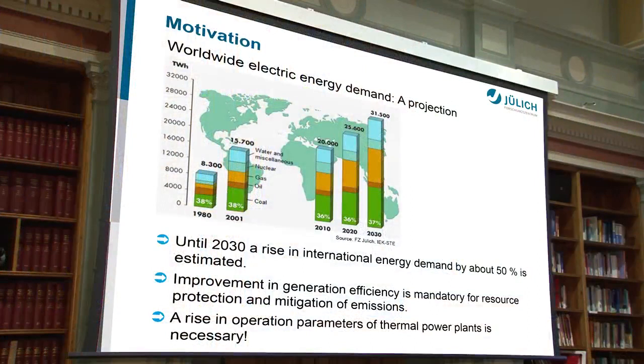Bernd Kuhn of the Forschungszentrum Jülich GmbH Institute for Energy and Climate Research in Germany was then invited to present the 2015 Charles Hatchett award-winning paper on behalf of his co-authors. By way of background, Bernd explained how world energy demand over the next 15 years is anticipated to rise by 50%, which would place additional efficiency demands on current and future power generation plant. Increasing efficiency can be obtained at higher operating temperatures, which require steels with higher chromium levels to give the necessary steam oxidation resistance. However, without taking additional measures, creep strength could be substantially reduced, negating any potential benefits of attempting to operate at higher temperatures.